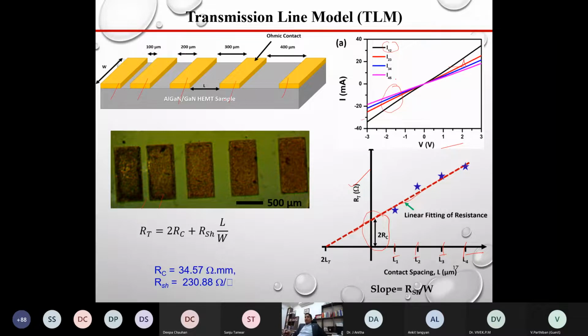What we have done particularly here is we have used aluminum, chromium and gold. So we have used tri-metals to minimize this contact resistance. Another one is the sheet resistance. We can calculate it from the slope; our device width we know. So we get a sheet resistance of around 230 and a contact resistance of 34.